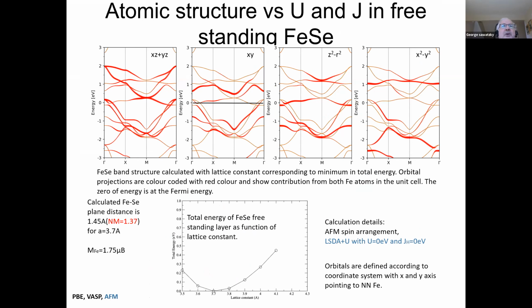And the reason is that if you have a local moment, you cannot have 2 electrons in every k state. This means that for these anti-bonding iron d states, relative to the selenium, you have to occupy more and more, higher energy anti-bonding states. And as soon as you occupy higher energy anti-bonding states, the bond itself is becoming weaker and the distances are going to become larger. And this is exactly what happens. We've done this study for the iron oxides, for iron halides, and every time, if you look at a low spin, high spin transition, you get the same kind of thing again.